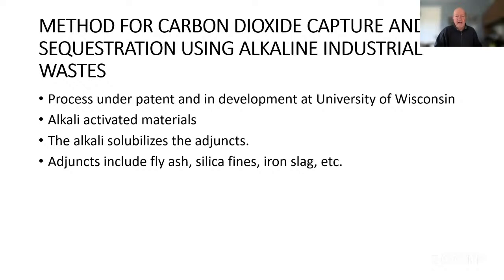But in addition to that, if you blow air, and this is what Lou was talking about earlier, if you essentially bubble air through that fly ash, it will absorb CO2 and form calcium carbonate, and you've got excess. You have excess calcium hydroxide in there, and so that calcium hydroxide will convert to calcium carbonate, and you'll end up with actually even stronger concrete as a result of that. And that's what these guys are doing.